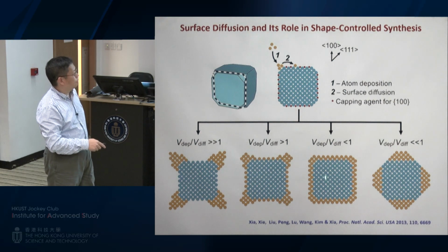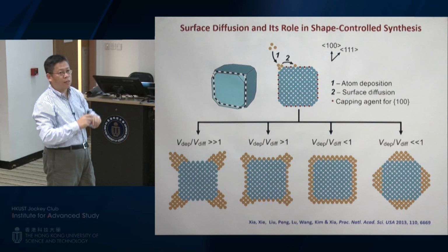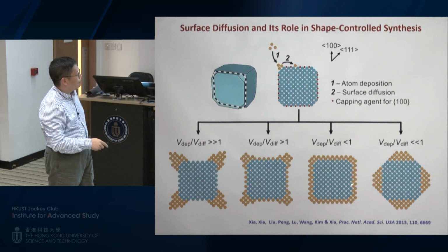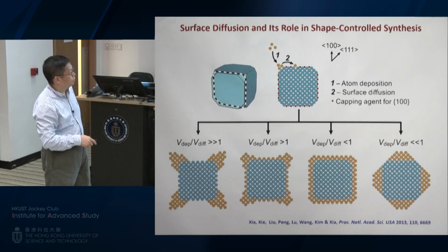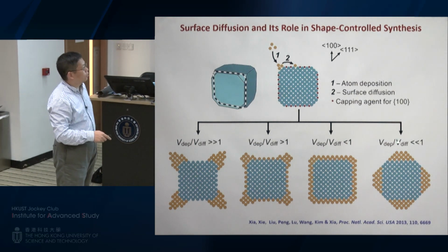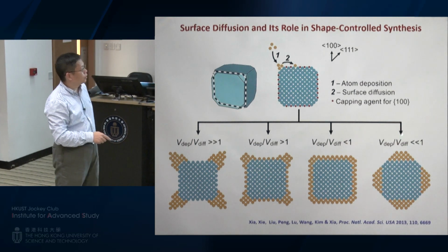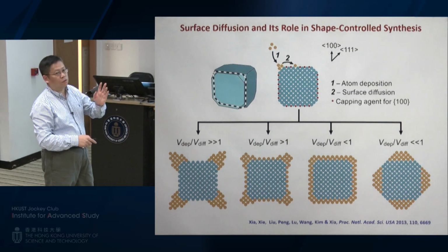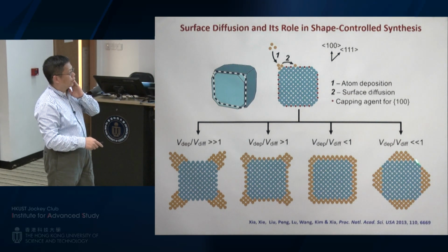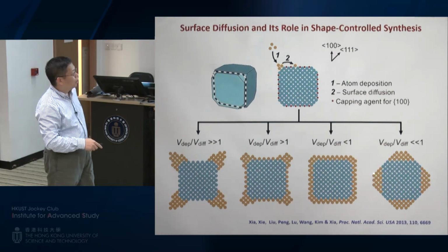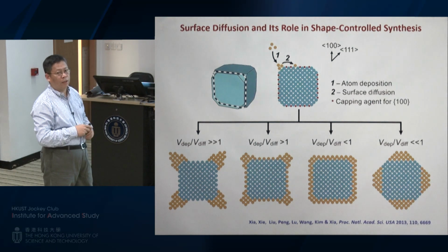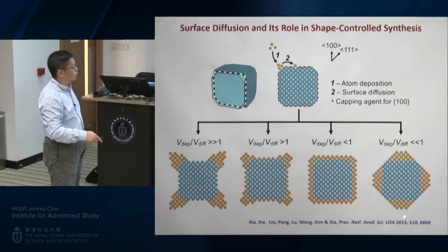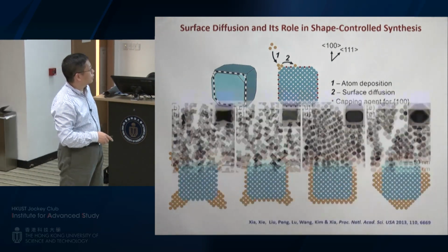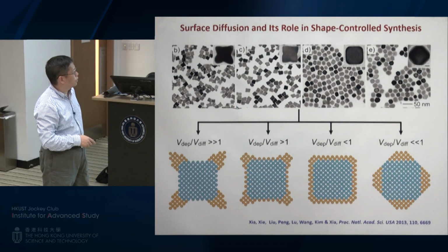So the core shell structure will have the same shape or morphology as the seed, just with the dimension slightly increased depending on how many layers of atoms you deposited here. If the diffusion is too fast relative to deposition, the atoms will do reconstruction. They may change the shape to give something more closely related to thermodynamically favorable shapes, like octahedron in this particular case. Anyway, you can observe all of these different morphologies by basically controlling these two ratios.